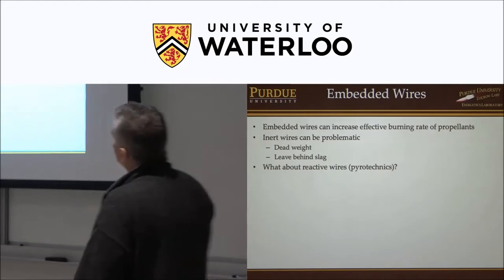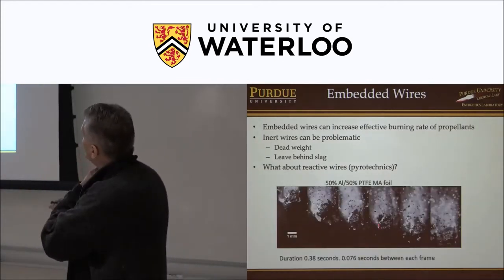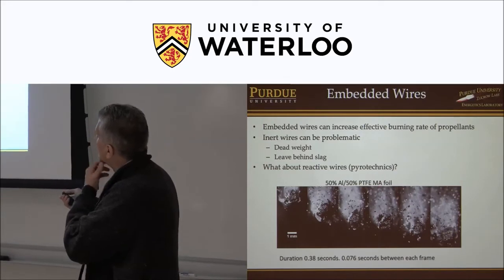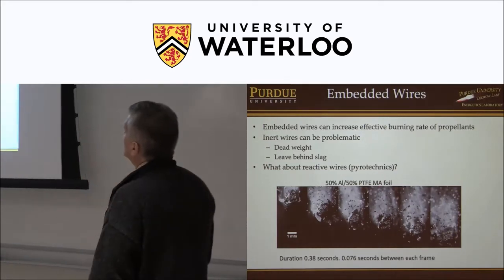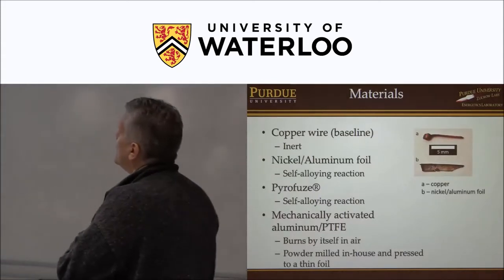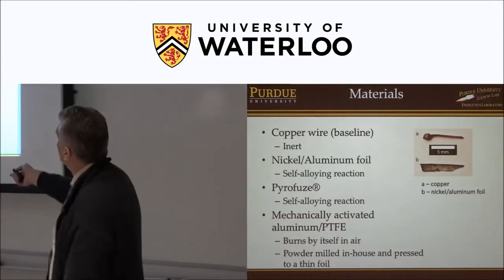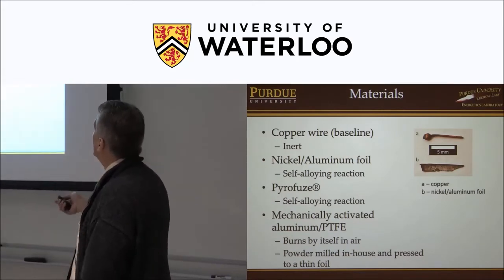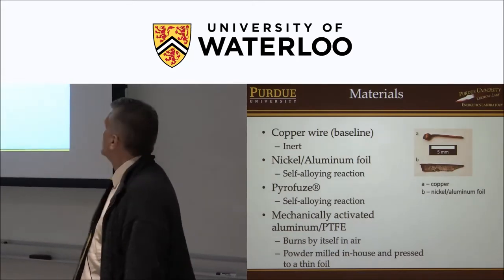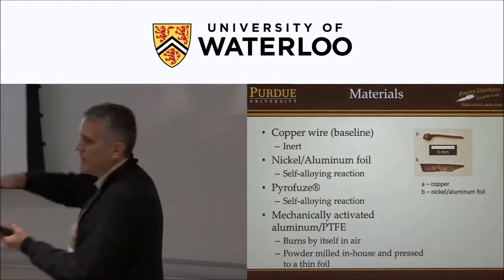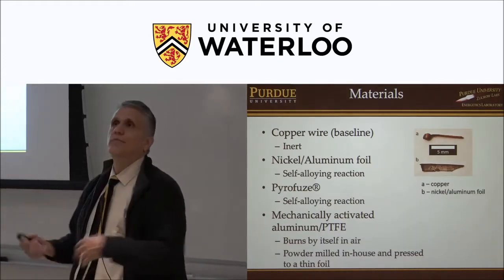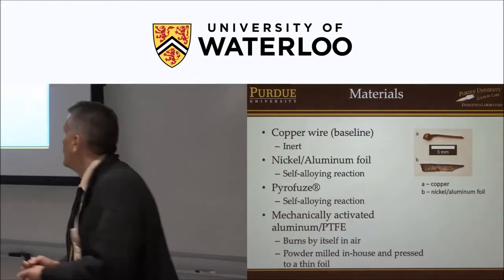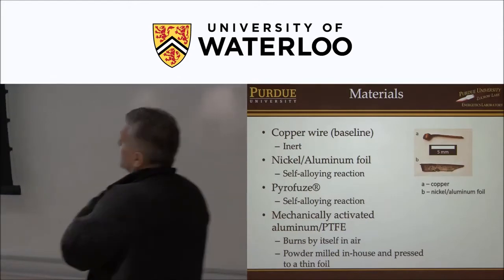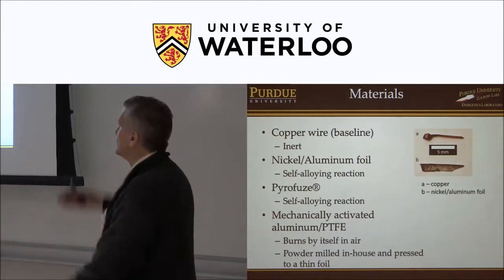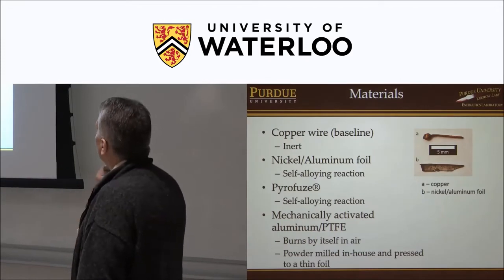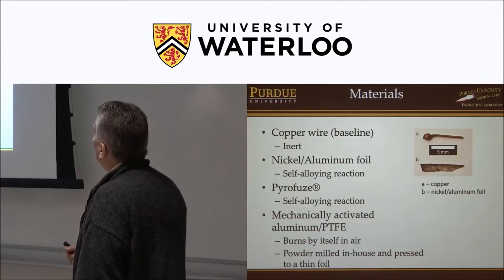So what about reactive wires or pyrotechnics? This is a 50% aluminum, 50% Teflon, and we made this into a foil. This is just burning by itself. We've looked at putting different wires into propellants and comparing them. The copper wire is just a baseline inert wire. There's a nickel aluminum foil that's a commercial product. Well, it's vapor deposited, nanoscale layers of nickel and aluminum. That forms an intermetallic reactive material. In fact, that material is used for a lot of applications, including welding of big screen TVs and stuff. So it's a commercial product, very fast burning, reactive.